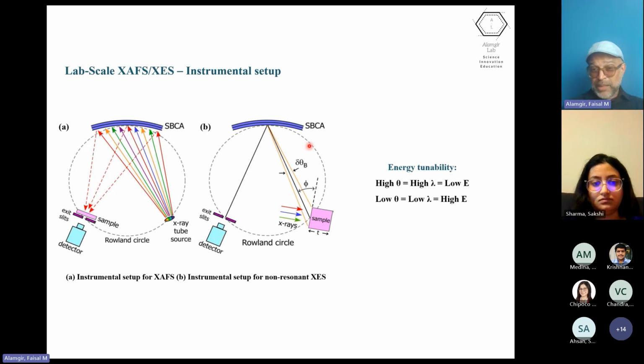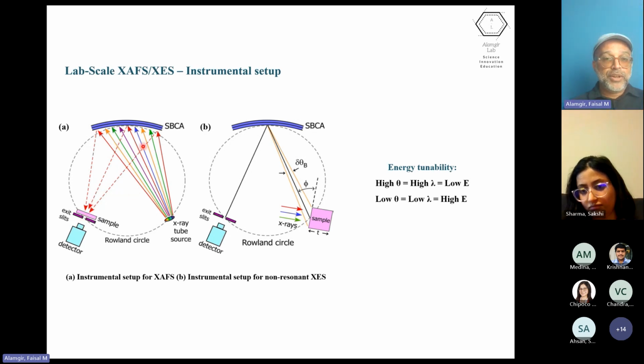In doing that, by changing the angle between the crystal, the source, and the detector, we can change the energy of the X-rays reaching the detector. So if we do want to do X-ray absorption, we use an X-ray tube, and the polychromatic X-rays coming out from the X-ray tube are then refocused, but also energy selected by the particular angle that the crystal is sitting at. That particular X-ray energy then passes through your sample and reaches the detector. So as we rotate the crystal, we are able to scan in energy and do an X-ray absorption measurement.